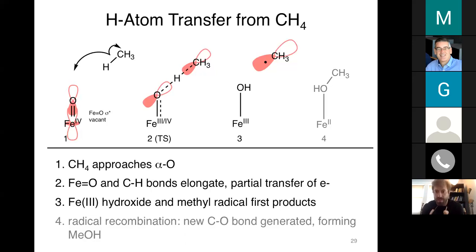And finally, in the subsequent step, moving from 3 to 4, the methyl radical will rebound on the oxygen, forming a carbon-oxygen bond. So in steps 1, 2, and 3, you ultimately have the CH bond transferring a proton and an electron into the iron site. So you reduce the iron by 1 electron. And in a subsequent step with CO bond formation, you further reduce the iron to its iron(II) state, which returns it to the reduced state of the active site.